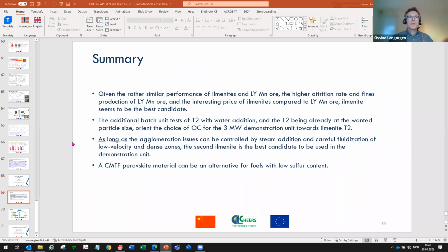So we have investigated some natural ores, and we have found rather similar performance between ilmenite and manganese ore. Maybe a little bit less gas conversion on the manganese ore. And it also has a higher attrition rate and fines production. Since the performance of the ilmenite is rather good compared to the manganese ore for the pre-processing, it seems to be the best candidate.